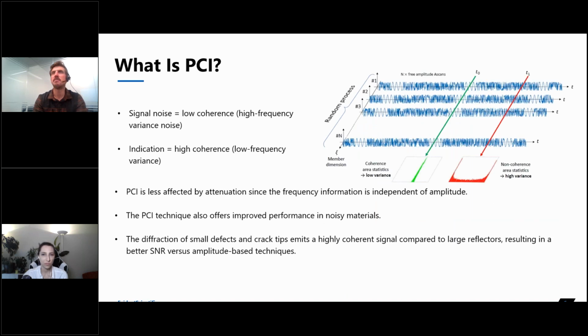How we can generate an image based off of that is what we find is that where we have background noise in our signal, all these parts here that are very high frequency, that's what we call the low coherence and high frequency variance noise, versus where we have a very coherent and uniform signal, which is a bit lower frequency. That's what we call our high coherent signal. This means that PCI is less affected by attenuation, since the frequency information can still be acquired completely independently of amplitude, which gives the PCI technique better performance when we're using noisy materials.